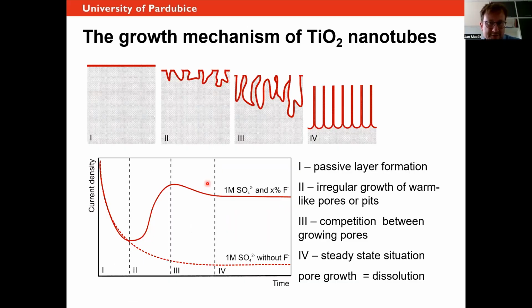More or less following this scenario. So what happens on the very surface of titanium is that you have this native oxide. As you apply the voltage, as the time goes on, there is some kind of, we could call it corrosion. So the fluorides actually penetrate to the titanium and they actually dissolve the titanium. At the same time, the just dissolved or etched parts are also oxidized. So there are some pores grown, and in the course of time, what happens is that the large pores become even larger. The weak pores actually die, and it's always like a natural competition, like in nature. So the stronger survive, the weaker die, and at the end there is this natural self-organization phenomenon, which makes the tubes arranged more or less in the same fashion, so that each tube occupies more or less the same area.